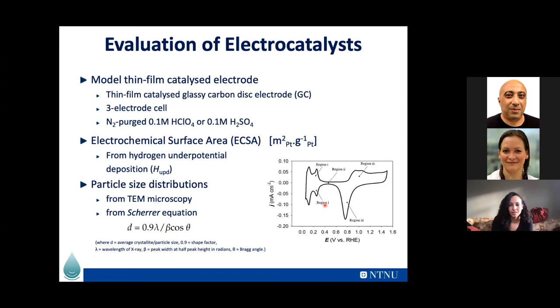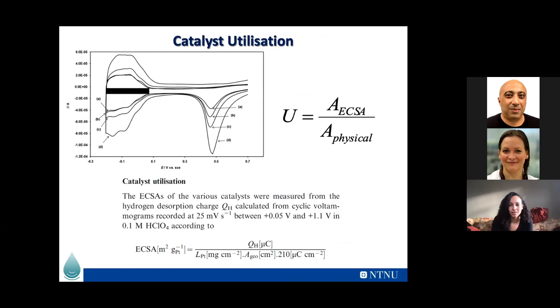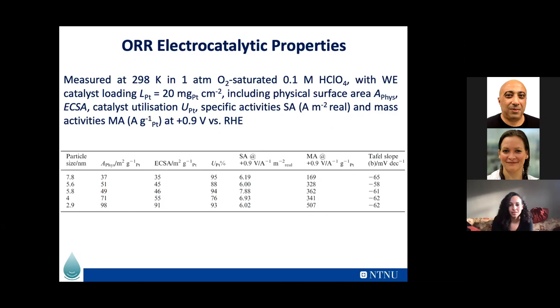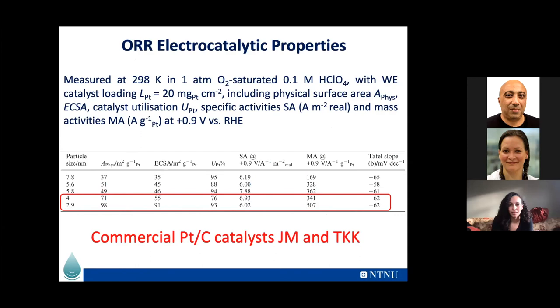You do, of course, your TEM microscopy, and on some occasions you use the Scherrer equation to get a guesstimate, or actually to ensure that what you found in TEM is on par with what you get from the Scherrer equation. This is another thing that people tend to forget: catalyst utilization is important. You can have the best catalyst in the world, but if that catalyst doesn't do anything towards the chemical reaction, then you have a problem. What we found is that our sonochemically produced electrocatalysts were on par with the usual suspects on the market, Pt/C and Johnson Matthey.